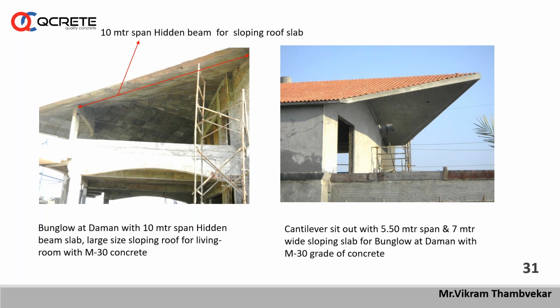So to avoid all such problems, we have to produce good quality concrete, and good application is also equally important. If application is not good, then making a good concrete is not useful at all. Making a good concrete, placing a good concrete, compacting a good concrete, and of course the curing factor. If we do not cure properly, regularly, frequently, then we won't get good strength.